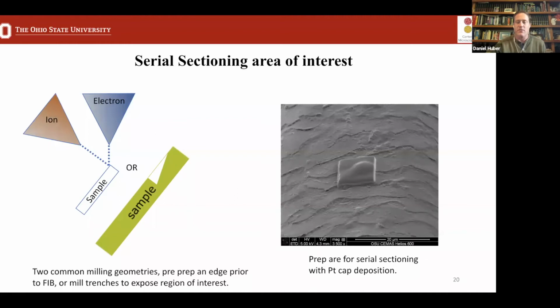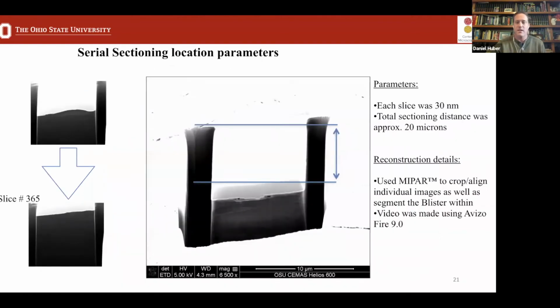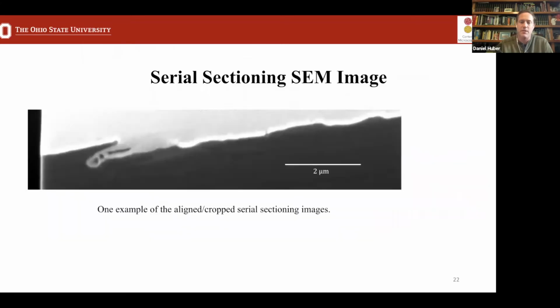If you look at the green specimen, we'll just trench into the material and expose an area that the electron beam can then image. So that's what we did in this case. We sectioned around the outside edge, exposing the area around the bubble that's been encapsulated in the platinum cap. And for sectioning, this is the sort of view where we would crop out all the rest of the information and just look at the area of interest for reconstruction.